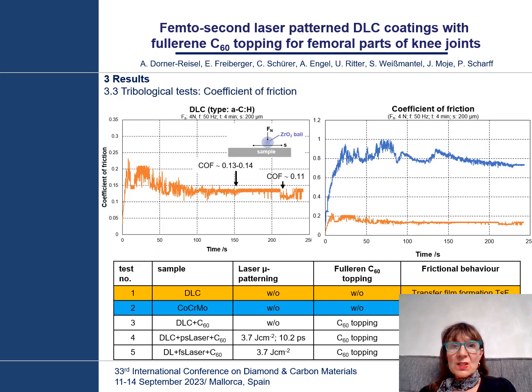Now we turn our attention to tribology. DLC has a coefficient of friction between 0.14 and 0.11 finally. While on the other hand, the uncoated cobalt, chromium, molybdenum, which was loaded by the zirconia ball, has a friction coefficient of 0.73 finally.